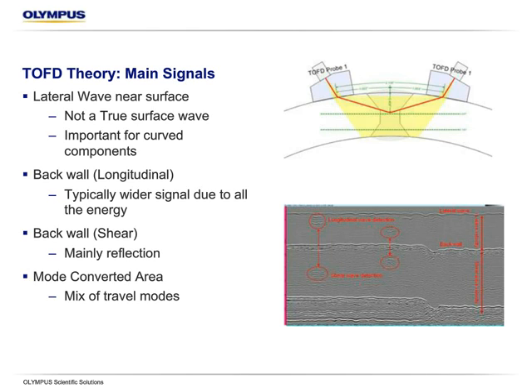So it's almost a near 90 in most setups, going across and then going through the coupling medium, being able to be transmitted into the receive probe. So again, this is going to arrive first. It's usually designated as 0 for depth purposes, or the top surface of a pipe or weld that we're inspecting. It's really important to understand that it's not a real surface wave. It can't be blocked out by damping with your finger.